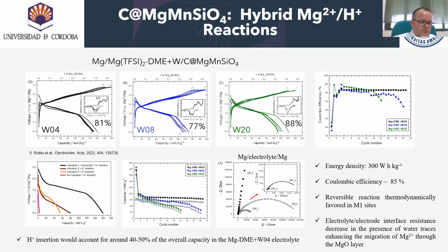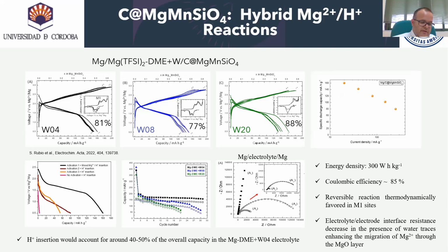Symmetric magnesium electrolyte magnesium cells reveal that the electrolyte-electrode interface resistance decreases in the presence of water traces. We can see here, this is no water. When we increase the amount of water, the semicircle is decreasing, enhancing the migration of magnesium through the magnesium oxide layer. The performance at different rates has also been obtained, and we can see the capacity fluctuated from 160 to 80 when we change the current density between 20 and 250 milliamperes per gram.